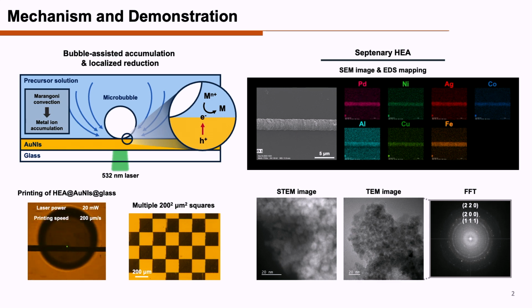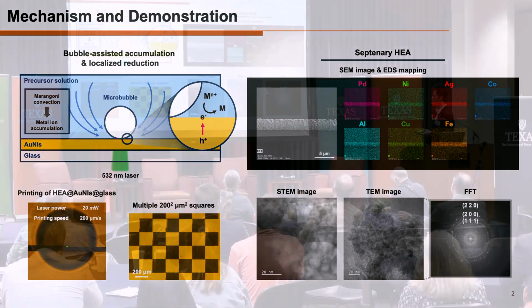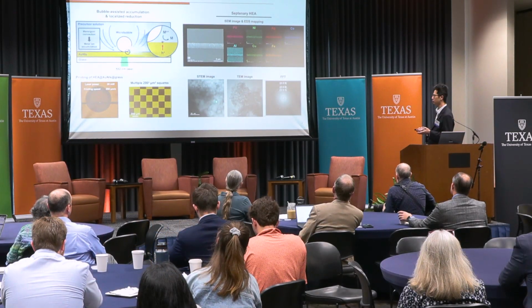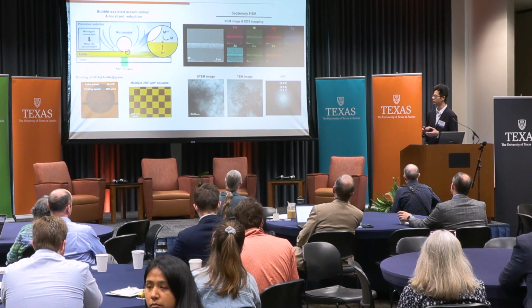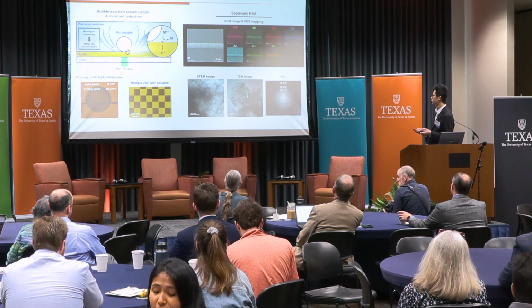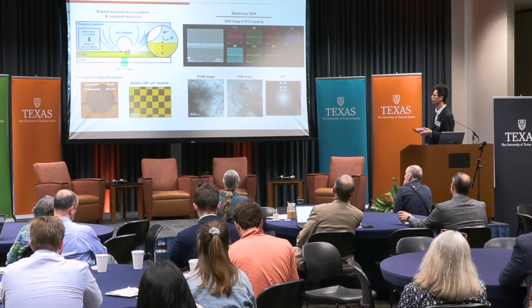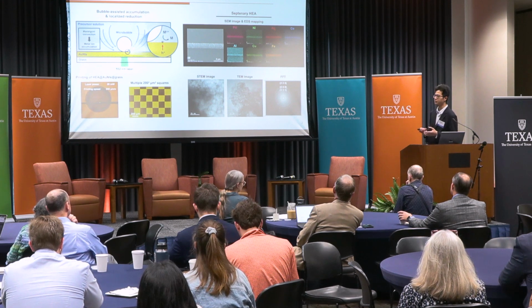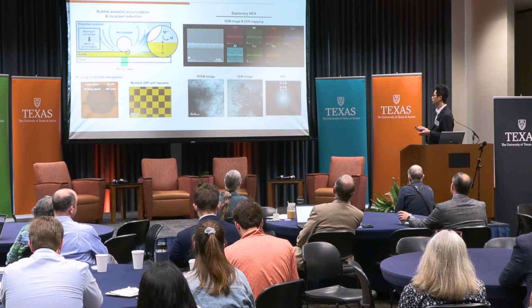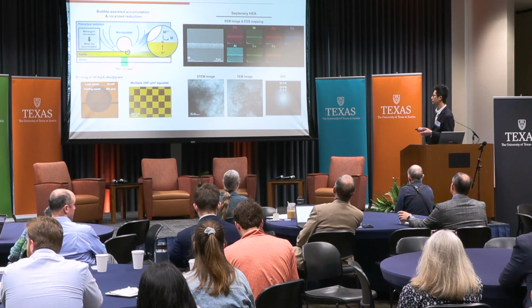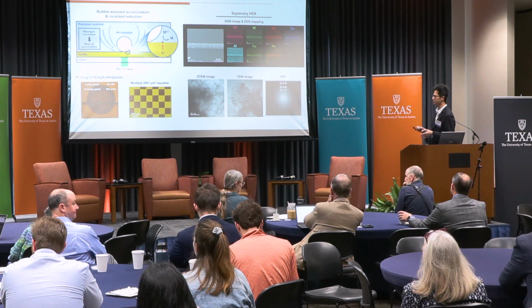And on the right side, we have demonstrated characterizations for these septenary high entropy alloys. In the first part, we do some SEM imaging and elemental mapping, and we can see that in this line structure, we have 7 elements inside. And also we do some transmission electron microscopy to see the crystalline information. From the STEM image, we can see that the structure is composed of a lot of small polycrystals, and it shows the polycrystalline nature of my material. And also in TEM, we can see most parts are crystalline. Maybe a little part is amorphous, but most of them are crystalline. And from the fast Fourier transform, we can see that the pattern looks like face-centered cubic. So we can confirm that these 7 metals sit in the FCC lattice.